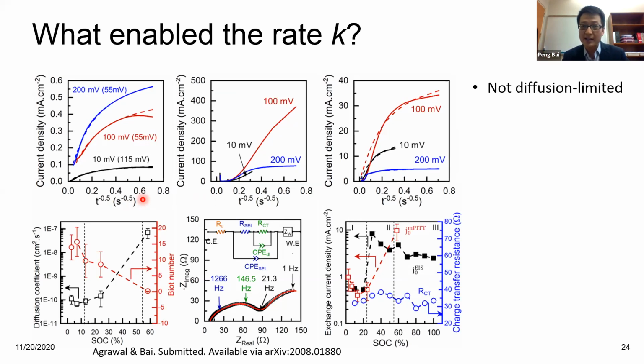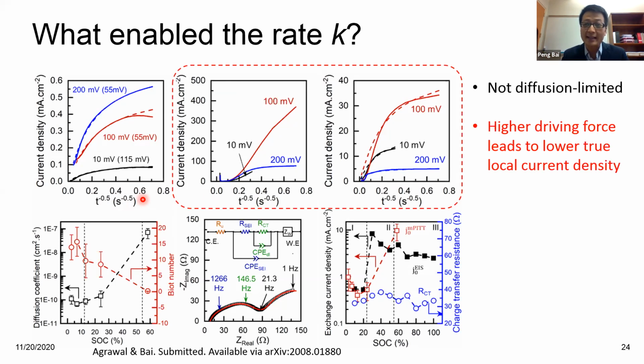But what's even more surprising is that it's not reaction limited either. Because look at these 2 panels here. You would imagine for any electrochemical reaction, when you have a higher voltage, the reaction should go faster. You should get higher current density. But guess what we obtained? When you have a larger voltage step, 200 millivolt, the local current density becomes lower than the 100 millivolt excitation. How would that be possible? Same thing here. When you have a larger excitation, the resulting current density is even lower than the smallest excitation. So higher driving force leads to lower true local current density. Why?